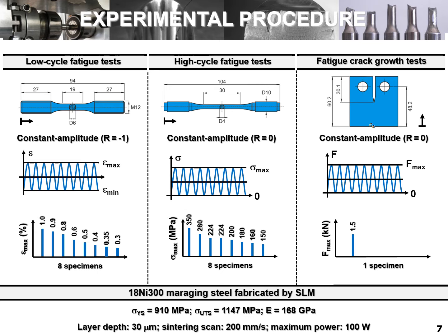High cycle fatigue tests under pulsating loading conditions for maximum stresses between 350 and 150 megapascals, and fatigue crack growth tests under pulsating loading conditions for a maximum remote force of 1.5 kilonewton. All the loading scenarios and the number of specimens tested for each case are represented in the slide.